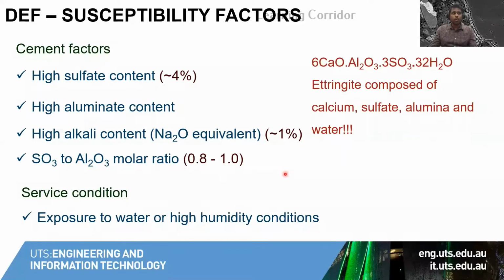And it's also about appropriate quantities. It's not that higher sulfate content means more ettringite precipitation. There should be an appropriate alumina content for the sulfates to react with. So the sulfate to alumina content should be around 0.8 to 1 in a molar ratio. That's the specific content for delayed ettringite formation to occur, to be deleterious.